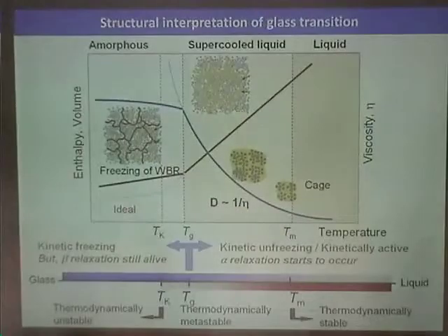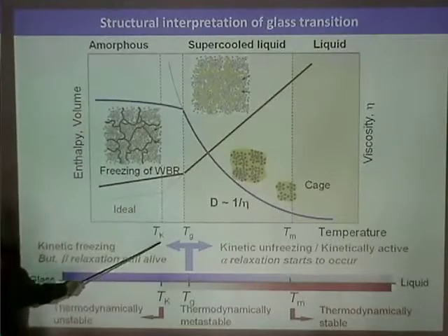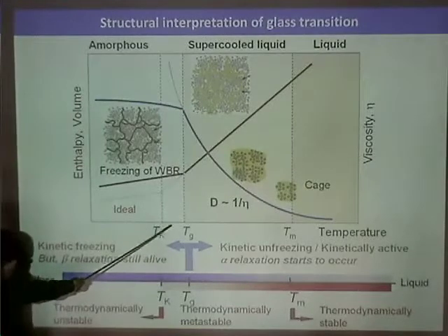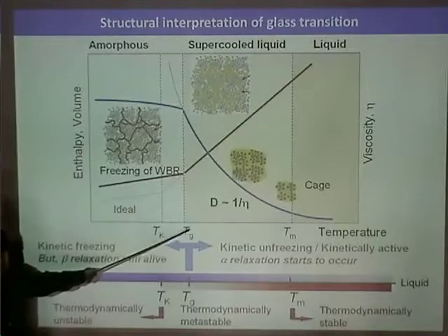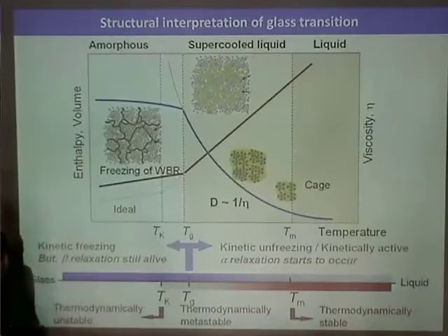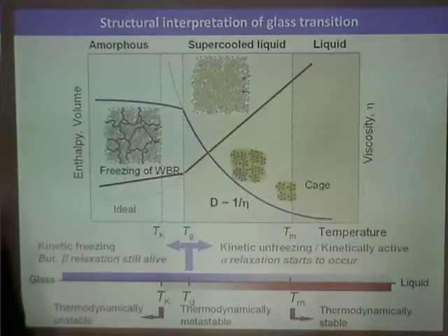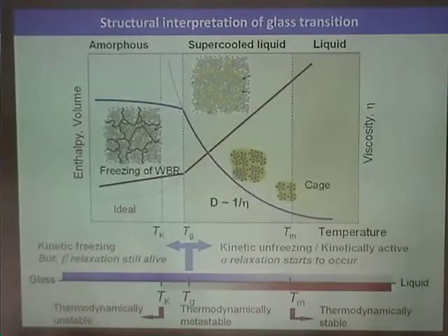You probably didn't mean that the blue line is below the extrapolation, did you? I'm sorry. In the amorphous state, the nominal viscosity is infinite. You have a yield. Ideal. Below TG. Once you have a glass, you would expect that the nominal viscosity, the extrapolation of stress over shear rate to low shear rate, is infinite. Well, that's by theory, but in experiment, the diffusivity is finite. But viscosity? Yes. So you mean the TK?